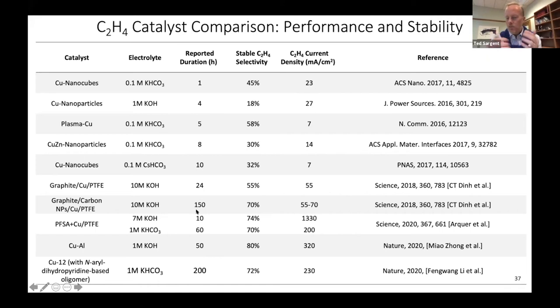But you'll see these and of course other works contributed by the wider community, there's a lot of activity in this area now, have taken us into the hundreds of milliamps, and even some above half an amp, into the 70s and even up to so far a kind of hero 80% Faradaic efficiency. And reported durations are now being measured in the 100 to 200 hours. In fact, most CO2 reduction works now typically give at least 100 to 200 hours of reasonably stable operating time, to show at least initial robustness on the path towards the tens of thousands of hours that are going to be required.